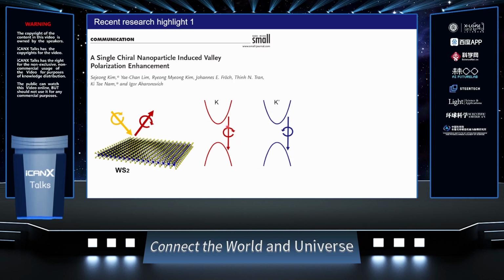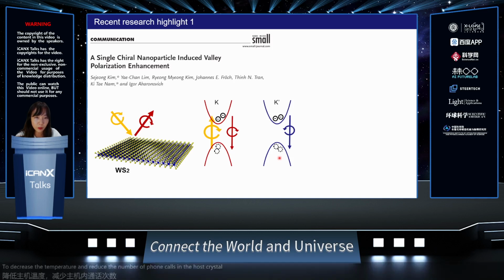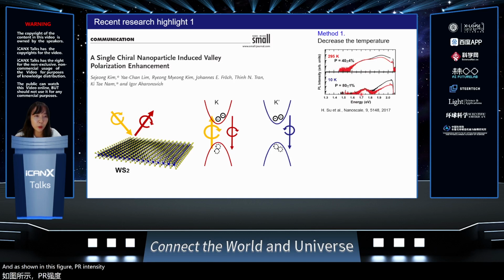However, in reality, this experiment is not obvious for observing the clear difference in the PL intensity. And here is why. If we excite one specific valley using a laser, then the exciton is created. However, due to the phonon-mediated scattering process, the electrons are redistributed, which results in observing PL from both valleys. Therefore, the easy solution is to decrease the temperature and reduce the number of phonons in the host crystal. And as shown in this figure, the PL intensity difference between right-handed and left-handed circularly polarized light, also called valley contrast, increases as the temperature declines. This means that the redistribution of electrons is suppressed due to the lack of phonons.